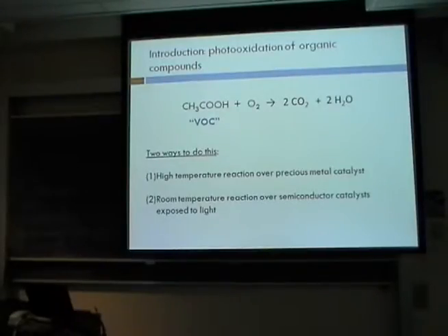For example, a photocatalyst like titania is often used in exterior white wall paints because it has a self-cleaning function. When sunlight shines on it and it's in the atmosphere, it will actually react carbonaceous material with oxygen pretty efficiently to make CO2 and water, so that you can get this self-cleaning action.